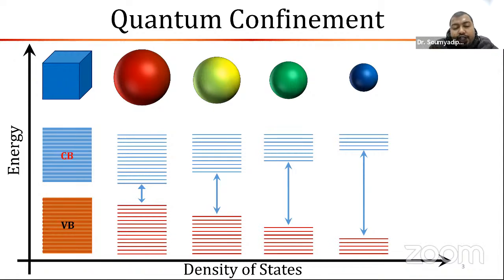So when we change the size of a quantum dot, we are actually changing the band structure. The band gap between the conduction and the valence band becomes higher and higher when we are decreasing the size of the quantum dots. Basically, we are confining the electron and the hole pair more into the system. So the band gap is increasing, and therefore the emission gets blue shifted.